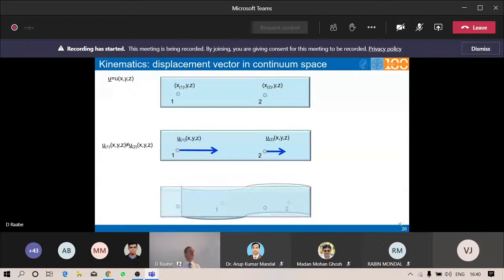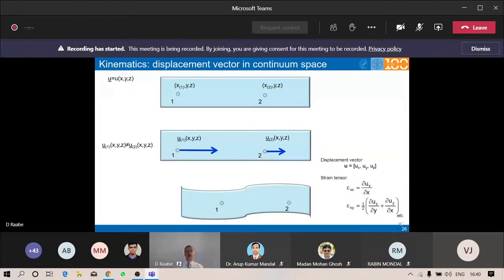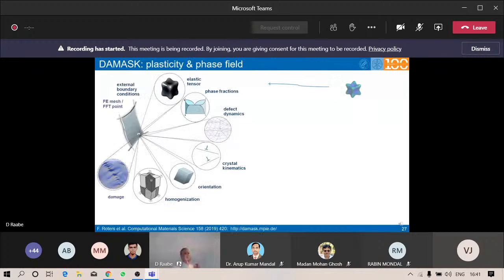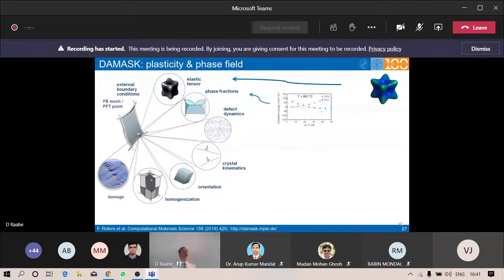That again sounds trivial, but that's how you formulate the displacement gradient. That means only the lateral gradient of the displacement field is what gives rise to distortion, to be accommodated by dislocations or a TRIP effect. That means the strain is just one possible linear, additive, or polar measure for the distortion that we typically use. The physical quantity that you need to match is the so-called displacement gradient tensor. And that is what you describe in terms of the individual dislocation fluxes in each of these directions. Because that mismatch that you see described here in classical continuum mechanics has to be accommodated by the shear carriers like dislocations or twins.